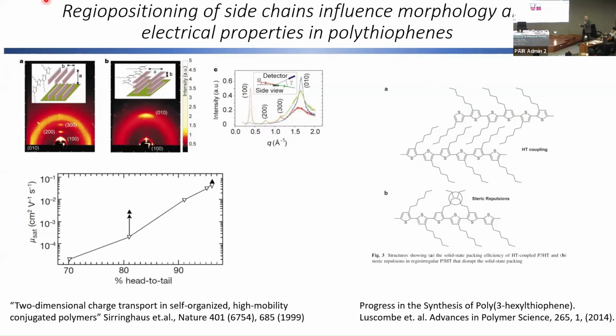And originally, the reason for the alkyl chains on that molecule was twofold. Firstly, it helped the solubility of the polymer to grow as you're synthesizing it. So in order for each repeat unit to be added sequentially along the polymer, it needed to remain in solution for the synthesis. So these alkyl chains helped that. The other reason is for the processing. If you want to use additive processing, such as inkjet or stamping, the polymer itself needs to be soluble.